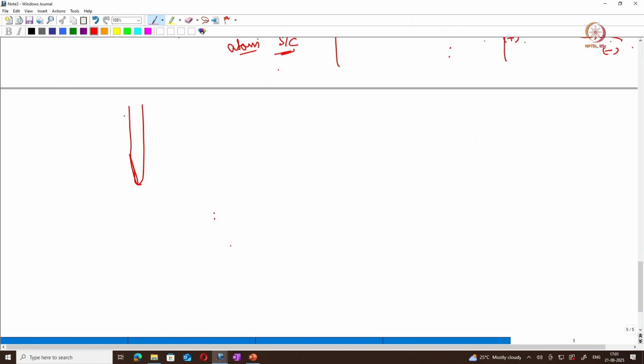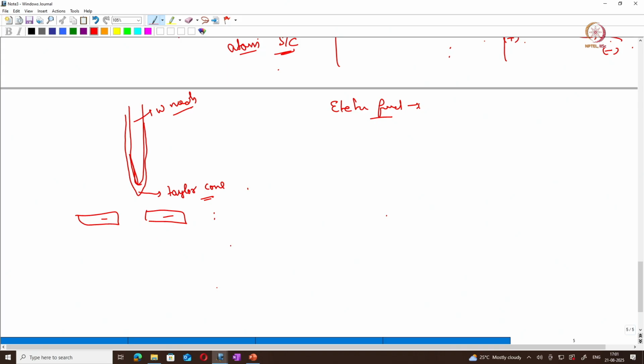Okay, and the liquid gallium will flow and it forms a Taylor cusp. So this is called the Taylor cone. Okay, and this is a tungsten needle. So when you put an extractor here, which is a bias of negative voltage, what will happen? The first thing is it will induce an electric field across, in front of the Taylor cone, which is nothing but liquid gallium. And this electric field pulls the gallium from the needle tip.